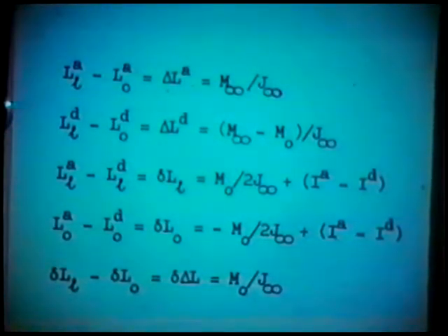For example, if you want to postulate a Fick's law mechanism, the diffusivity can be a function of the variables distance, concentration, and time, either altogether, separate, or in non-separable functions. So the results have total generality, requiring only local equilibrium within the membrane between its heterogeneous parts, for sorption.